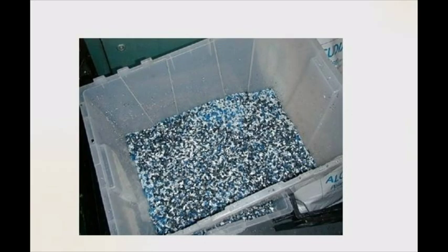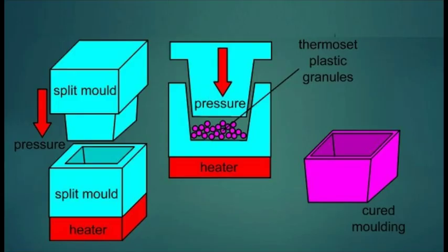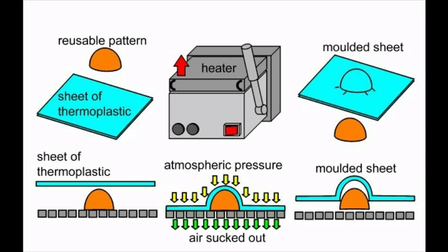Vacuum gives a pressure differential of about 1 atm, atmospheric pressure. We can add positive pressure on the other side for a total differential of up to 10 atm. Better output but cost increases. Sheet material needs to have reasonable form stability when heated. It needs to have a fairly high relative molecular mass.